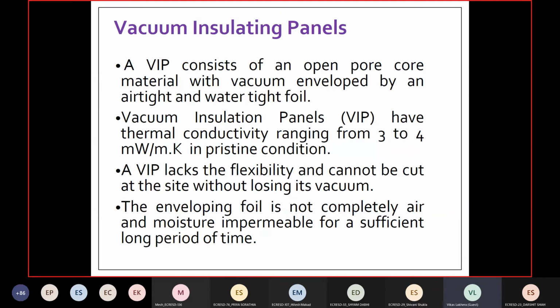So this is the range of conductivity. You are able to get in the range of 0.004 watts per meter Kelvin. So almost you can say 10 or more than 10 times lower than the lowermost value which you can get from other insulations. So vacuum insulating panels are good, though it is costly.